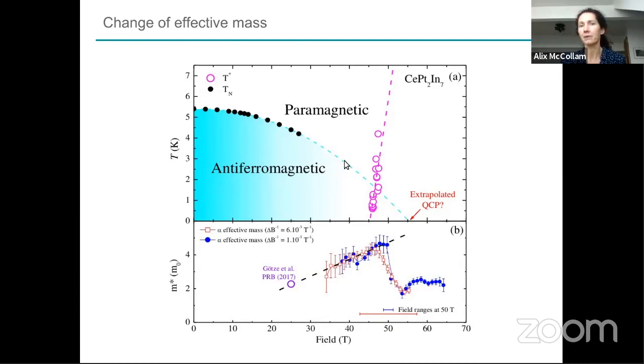So we would like to try to expand the heat capacity. It's not possible to do magnetic susceptibility because the samples are very tiny platelets, and we can't get enough of a signal from a susceptibility measurement to try and get a thermodynamic signature of this phase transition. So this extrapolated QCP is indeed, you know, imaginary. It doesn't have any basis, and it could be anywhere. One of the things that we're thinking about is whether it could be related to the endpoint of the valence transition, although you would expect the endpoint of the valence transition to be maybe at negative temperature in this system. Somebody asking a question?